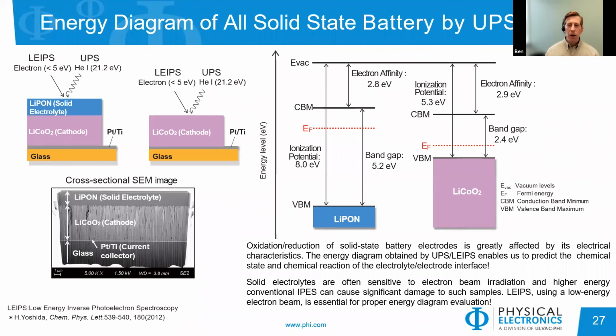With LEIPS, we are actually irradiating the sample with electrons, and then it's producing photons that we can detect. What that allows us to do is get information about both the valence band side of things and the conduction band side of things. So we can calculate things like the ionization potential with UPS and also the electron affinity with LEIPS. And so with these two different materials, the LiPON and the lithium cobalt oxide, we can characterize the electronic properties of these two materials as well.